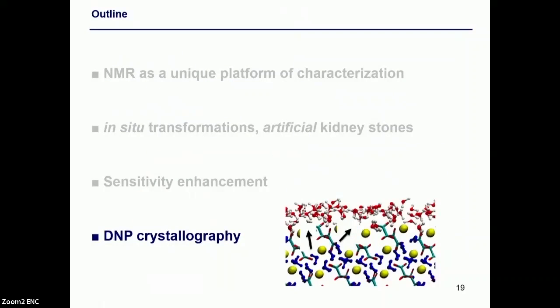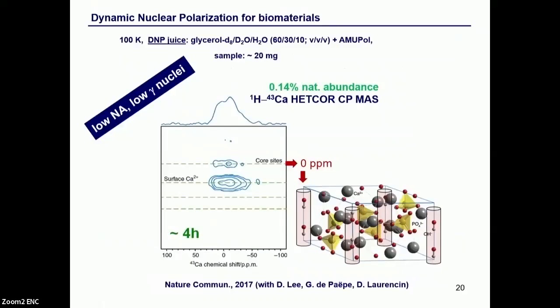Now, the last part of my talk will be devoted to some snapshots related to DNP, and I will give you at least 3 reasons to do DNP in the framework of biomaterials. The first one is related to low natural abundance and low gamma nuclei. You could tell me, okay, you are working with biomaterials, what about calcium-43 NMR? Calcium-43 NMR is a nightmare from the sensitivity point of view due to 2 things. First of all, it's a low gamma nucleus, and the natural abundance is really small. It's 0.14%.